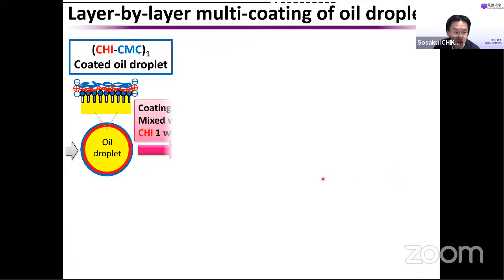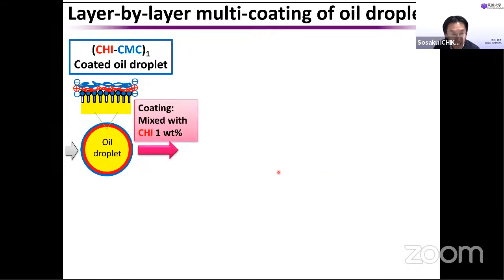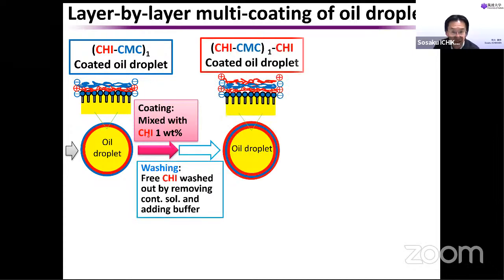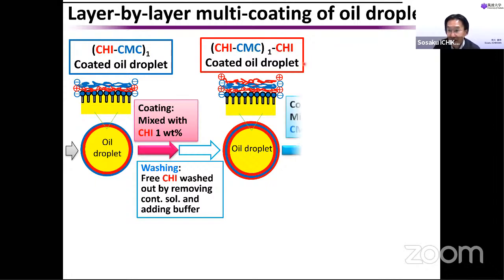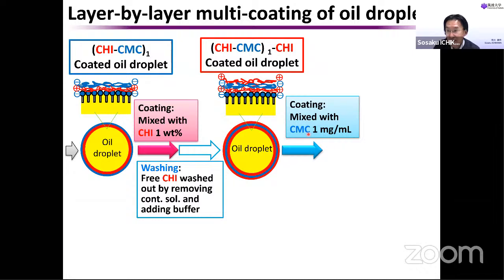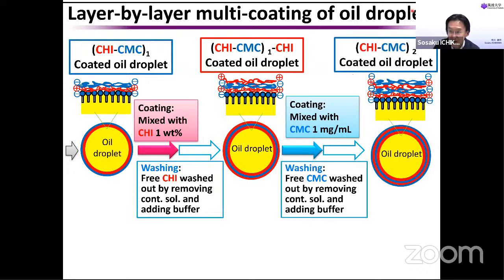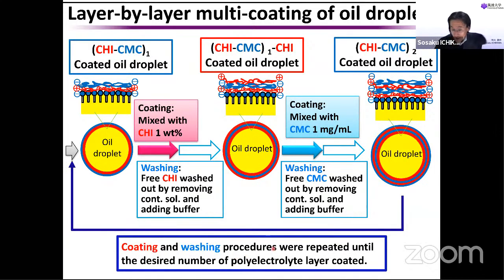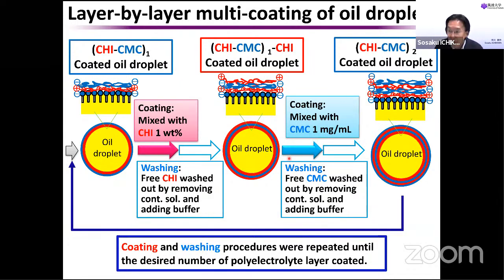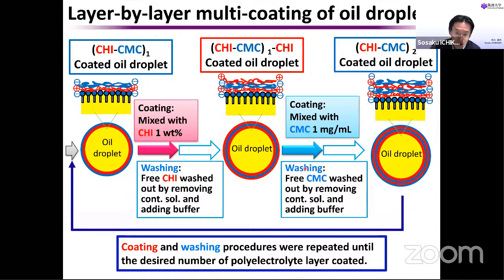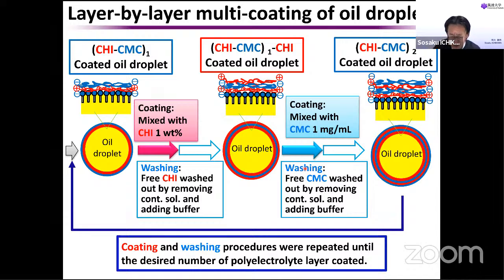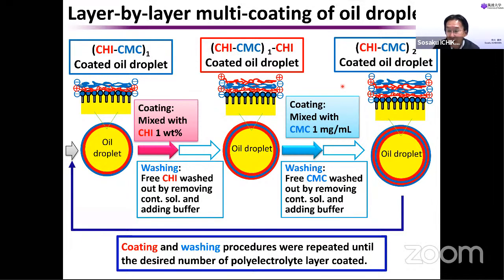So next is just a repeat of the coating. Next we add chitosan. Then we get the three layers: chitosan, CMC, and chitosan. Then we add CMC. We get chitosan, CMC, four layers like this. Then we can repeat this step. Then we can control the number of layers on the surface of the oil droplet. Then we can control the stability and release property by the number of the coatings.